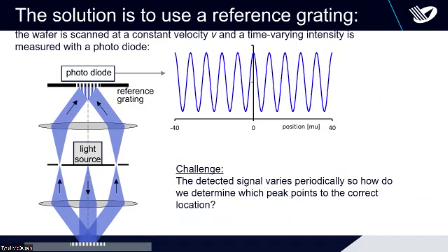So basically what you do is you do the same experiment, but replace the camera with a photodiode. And then the trick is you put an additional reference grating in front of the diode. So that's the same grating that we would, in principle, use for the alignment target. And that means when you now shift the alignment grating, you either align the lines of this grating on the reference grating, or you shift them such that the light goes through. So you get a signal that looks like this, just a nice periodic modulation on the photodiode. Now from that, you know when you go through the grating, but you haven't really found the location because you get a lot of maxima at the same height. So that doesn't really get us there yet.